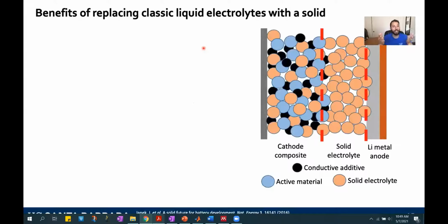So one thing that we can envision is moving away from these liquid electrolytes towards a solid. And our battery architecture in that would look like a cathode composite, which is composed of our active material and electronically conductive carbon additive, as well as a solid electrolyte. And it's this solid electrolyte that we're going to pay a lot of attention to today. So it also acts as a barrier between our lithium metal anode and our cathode.